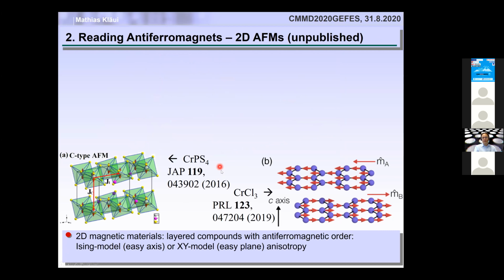So one very exciting materials class that we've been working on are these 2D materials, where you can also do electrical readout. And these 2D materials are exciting because, for instance, in this system here we have a trihalide, chromium trichloride. It's a layered antiferromagnet, meaning that one layer has the magnetization pointing to the right. So if you have a monolayer of this material, it's just a ferromagnet. But if you have a bilayer, then it's a fully compensated antiferromagnet because the two layers are anti-parallel. And if you put a third layer on top, again, you have one layer to the right, and so on. So this is really nice because by building blocks of this, you can tune between ferromagnet and antiferromagnet.